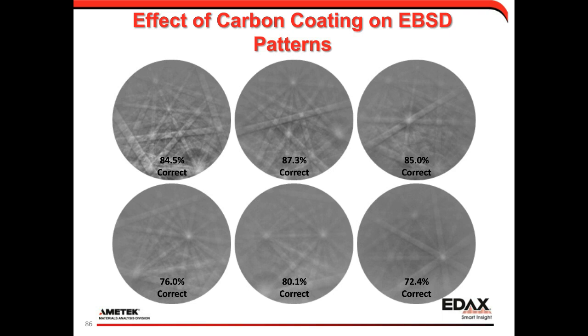The problem with this, of course, is you have to be able to control the coating thickness. And so we use an instrument that has a thickness monitor. Sometimes you have to experimentally figure out how to control that thickness.